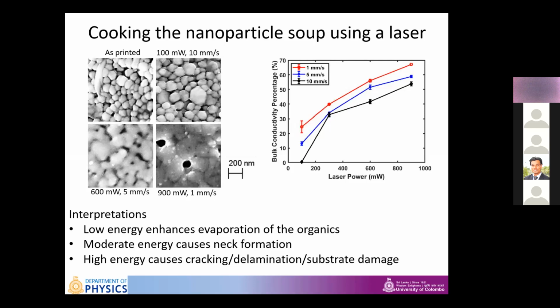On the left-hand side, I show some of the micrographs of the conductive trace at different energies and speeds. At relatively lower laser energies, for example, 100 milliwatt at 10 millimeters per second, that is the second picture on the first row, the microstructure shows not much difference compared to an as-printed trace. As-printed trace means you just print it and let it dry, you don't do any heat treatments. That is the first micrograph. So between first and second micrograph, there's not much difference.